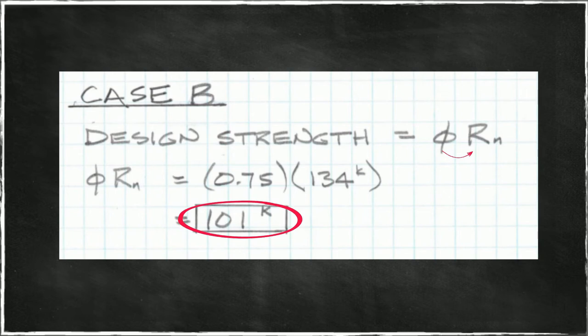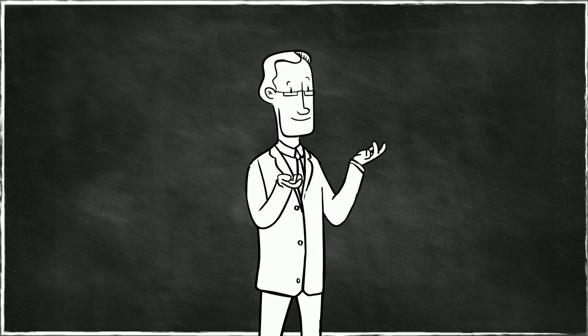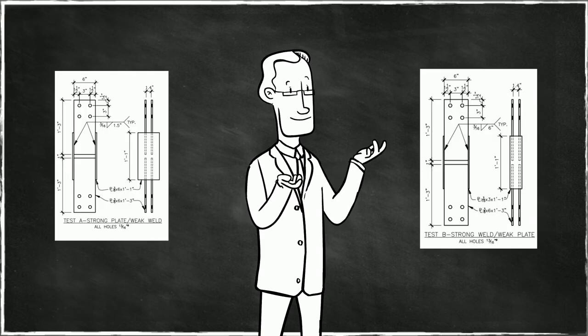Let's compare our nominal strengths of welds to the nominal strength of the plates. In this case, and it's the same equation as before, we'll use area of 3/16 inch times 3 inch for the plates. These are smaller plates. There are two of them times the tensile strength of the plate material. That leads us to 65 kips. 65 kips nominal strength for the plates is less than the 134 kips we calculated as nominal strength for the welds. Therefore, we expect the plates to fail before the welds. And we will now proceed to fabricating these specimens.